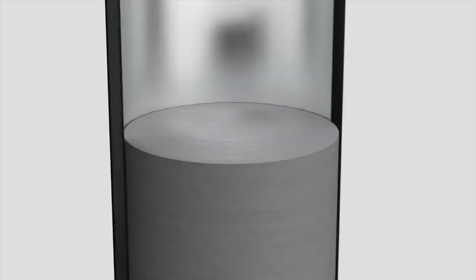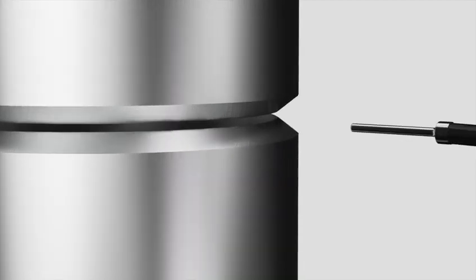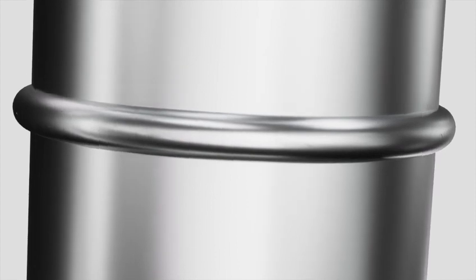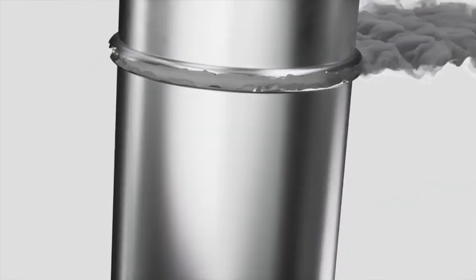High alloy tube repairs using a grade such as T91 require purging when the system cannot be blocked and are conventionally dammed on each side of the butt weld. A purge needle or gas lens is placed up to the open gap in the butt weld, and with a conventional repair, this is the only line of defense for shielding. If oxidation occurs due to a lack of backing gas, this discontinuity can render a crack in the root and will ultimately cause service failure.